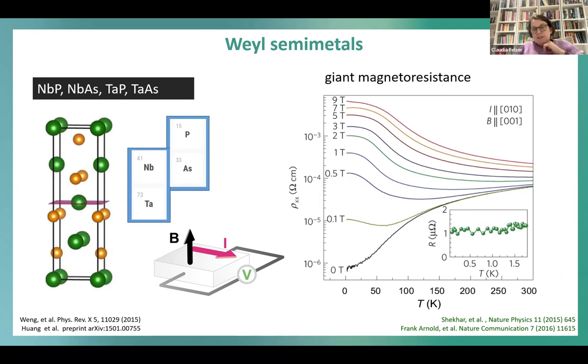And if you see the zero Tesla line here at the bottom of the resistivity curve, you see these wiggles, and these are quantum oscillations. This is also very typical for these topological materials. They show very nice quantum oscillations, and you can get the position of the Fermi energy and the Weyl points very nicely out of them. For niobium phosphide, it was a little bit tricky because the Weyl points were not directly at the Fermi energy. So it was good that we made nanowires, which we see on the next slide.